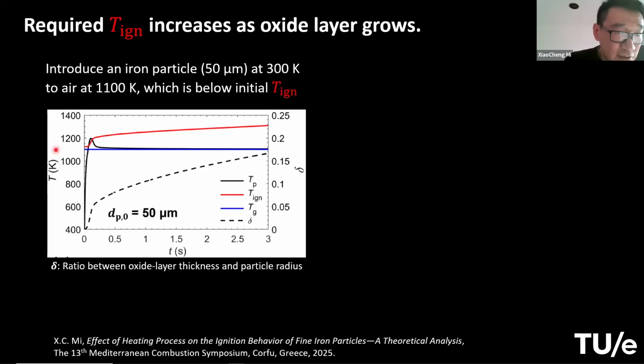You see here, the black line is the particle temperature. It increases very rapidly to the gas temperature. It goes a bit above the gas temperature, but it cannot undergo thermal runaway, so it will cool down, eventually reaching the same temperature as the gas.